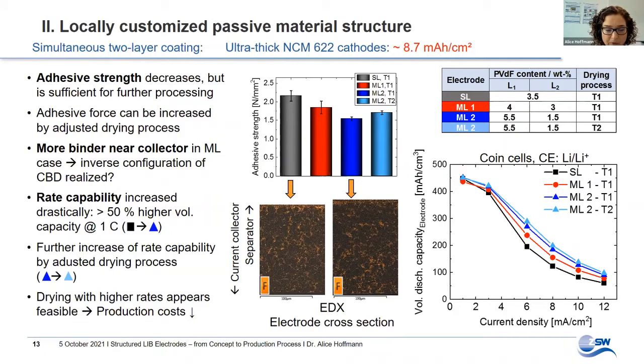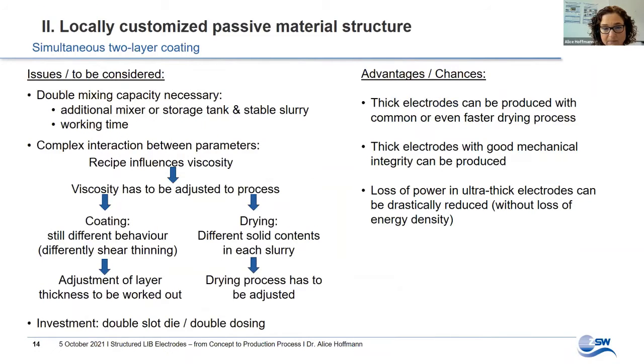Alternatively to improving the performance, the two-layer coating seems also useful to produce electrodes with the same properties, but with a faster drying process, which can be good for reducing the costs. As a brief overview of issues and advantages of the simultaneous two-layer coating, it has to be considered that a double mixing capacity is necessary, which means either an additional mixer or at least an additional storage tank. Also, additional working time is necessary. And I'd like to mention again the complex interaction of slurry parameters, which demands the corresponding time for process development.